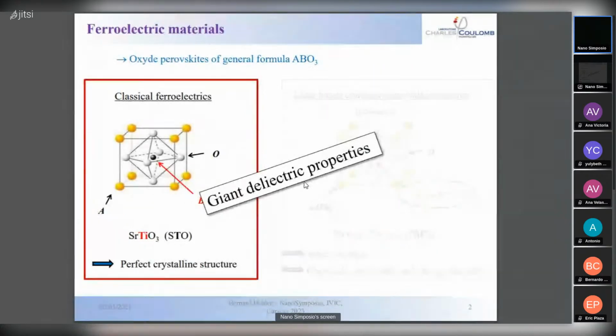So the materials I will be talking about today are oxide perovskites. Oxide perovskite is a wide family of materials with general formula ABO3. And most of these materials exhibit ferroelectric character. So the general structure of these compounds is cubic, with an octahedra here made by oxygen atoms. And at the center of the octahedra, you have the B site, which in the case of strontium titanate, SrTiO3, is the titanium here. So strontium titanate is a perovskite material which is very, very well known, by the way.